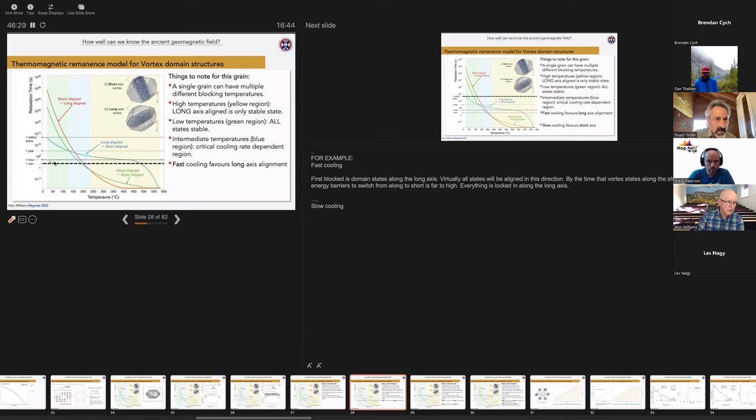And of course, these PTRM failures are intrinsic to the domain structure, of course, and nothing to do with chemical alteration. And although not often done, the PTRM tail check shown here by this green rectangle is also very large. And this is an indication of the failure of the reciprocity of the blocking temperatures. If we look at a cooling rate much closer to the laboratory rate, this one is cooled over 6,000 seconds. So that's about 1.7 hours, we see that the sample now passes the PTRM check from these red triangles, but still fails the PTRM tail check. And the blocking temperature reciprocity failure indicated by that tail check at 175 degrees centigrade, then contributes to the curvature of the Arai plot.